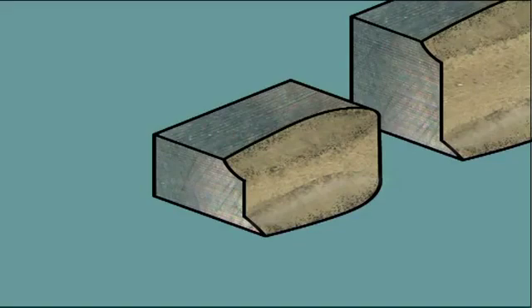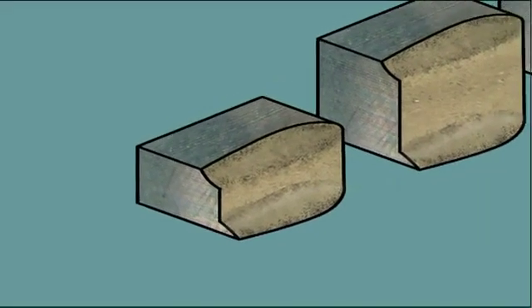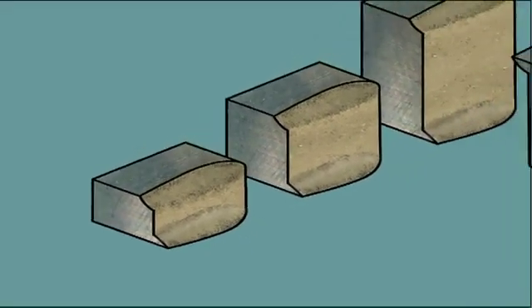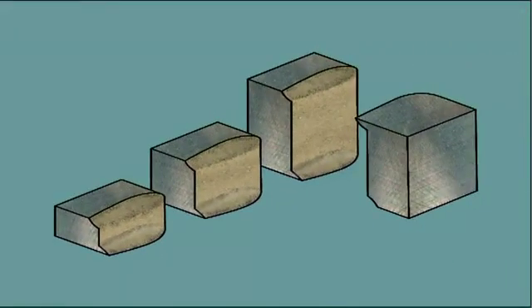In this case, a measurement of plane strain fracture toughness can't be made, as the value obtained would be too large. Fracture toughness tests, therefore, sometimes need to be carried out on extremely thick specimens.